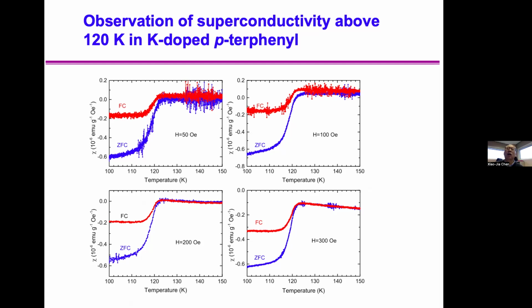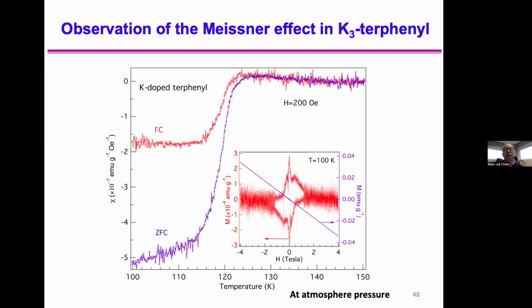You can see here the only elements are the lighter elements, carbon and hydrogen, similar to what we discovered in hydrides. When we take the measurement, I enlarge the figure here. You can see the magnetization versus the magnetic field. You can see a diamond shape here. That indicates we indeed reach the Meissner effect in this system, but this happens at ambient pressure.